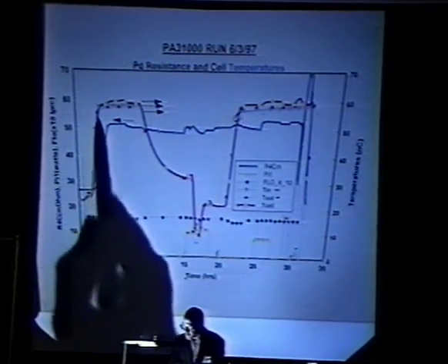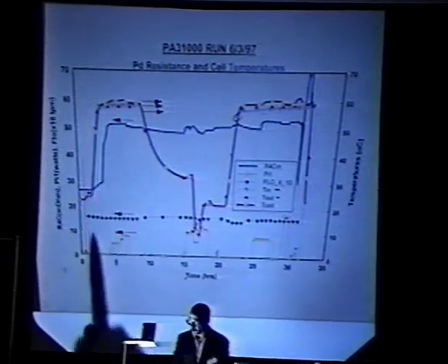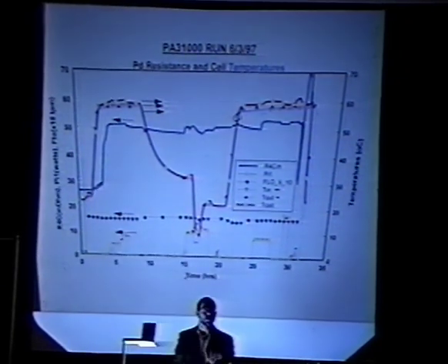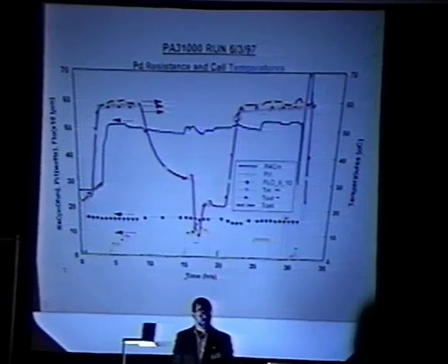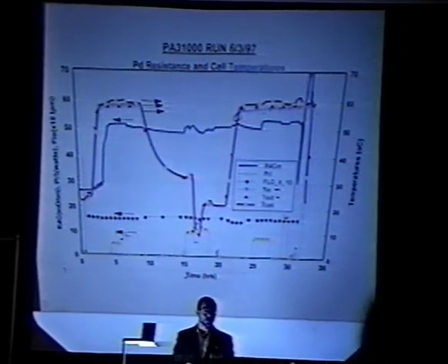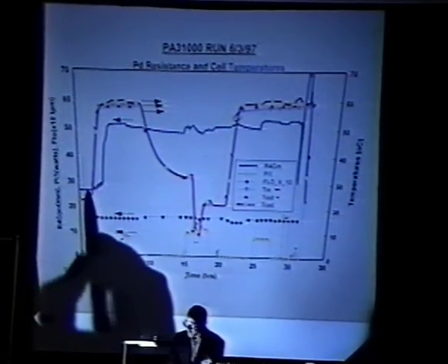This particular run started off everything near room temperature. And as I heat the cell, this is using the flow calorimeter, just power it up to a set point of 60 degrees. This right in here is where the resistance of the film goes up, that I'm real convinced is an increase due to the thermal expansion of the material. Basically, it's the thermal coefficient of resistivity. If you go and look that up in a table, it says it's about this amount. So we're looking at most here from somewhere on the order of, I guess, 27 to 29 milliohms of increase.